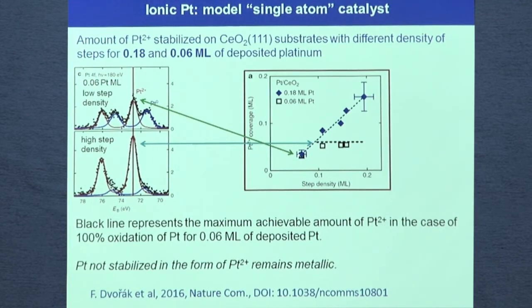And you can see that for low density, platinum 2+ concentration is here. But by increasing the density of steps, we are increasing the concentration, but after that we have a plateau, because all platinum is fixed at the steps in form of Pt2+. If we deposit a higher amount of platinum, we have an increase of platinum 2+ concentration, because more steps means more sites for platinum deposition or platinum anchoring on the specific sites.